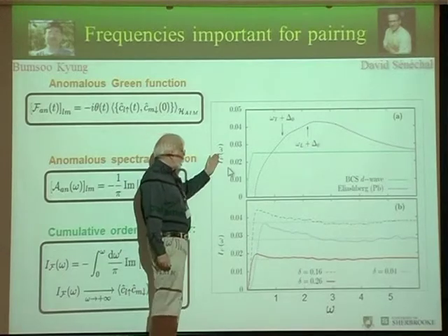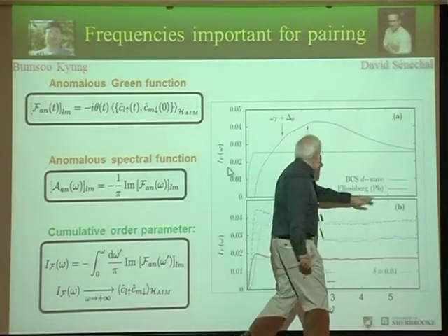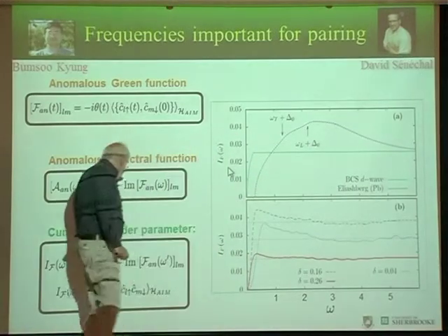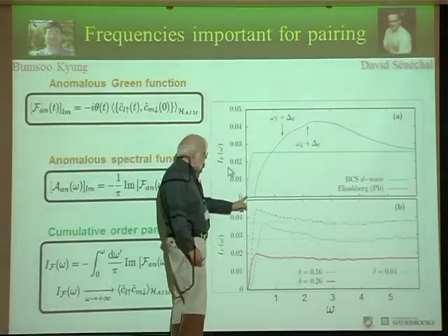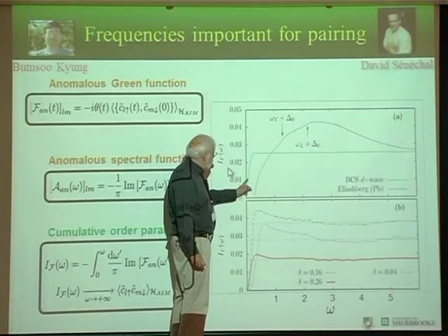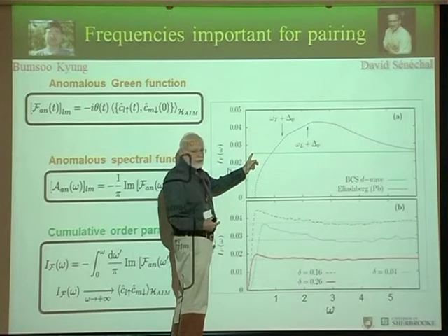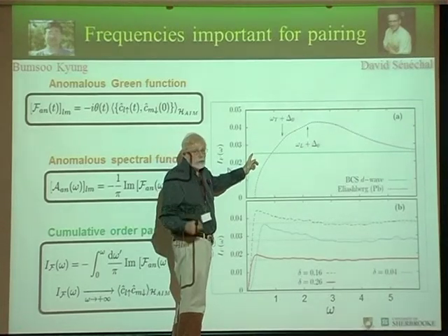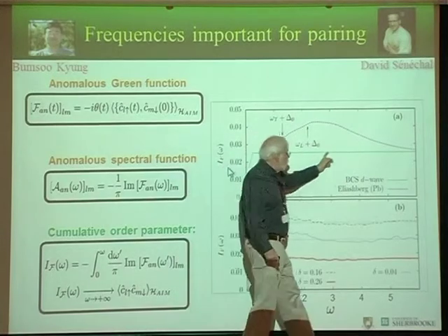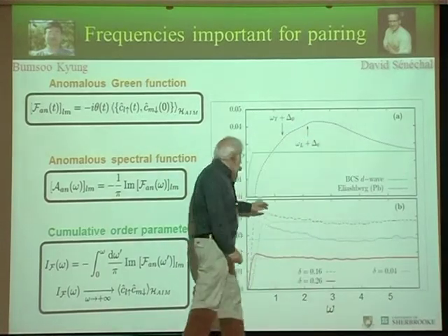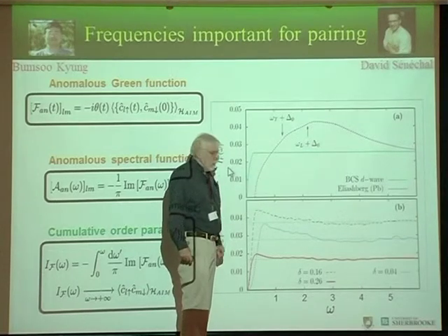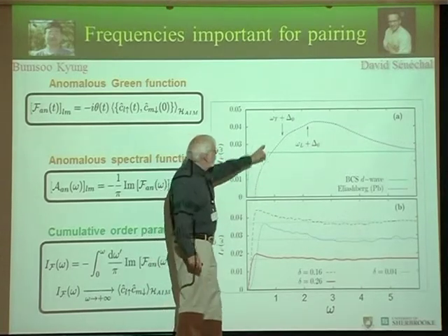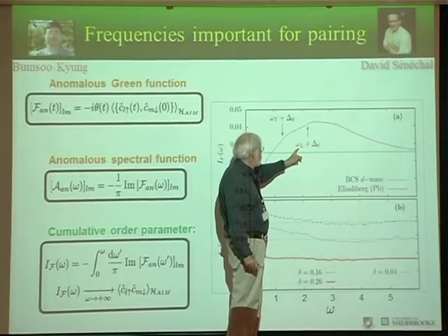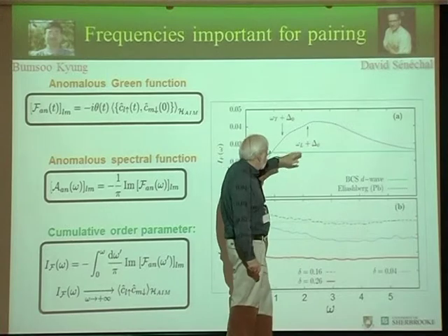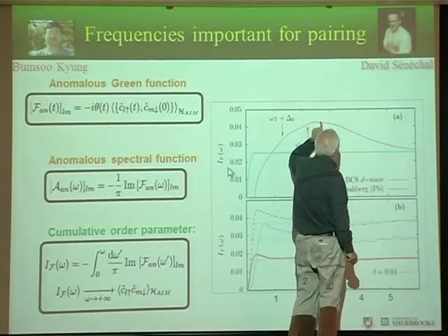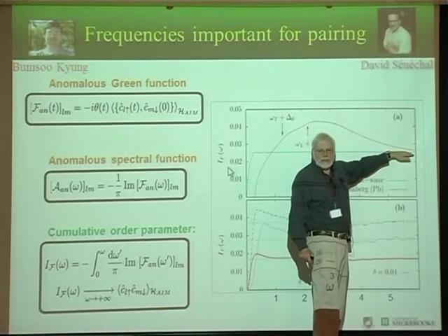So this is the cumulative order parameter as a function of frequency, and that's this upper bound here. This is for a BCS d-wave superconductor. It goes up until the cutoff, because in BCS there's always some cutoff, the Debye frequency, and then you've reached the asymptotic value. Now this is a calculation for lead, the dashed line. It is shifted by the gap. You see the transverse phonon frequency and the longitudinal phonon frequency shifted by the gap, and you see that it overshoots the asymptotic value of the order parameter.